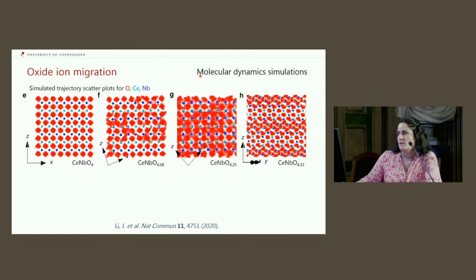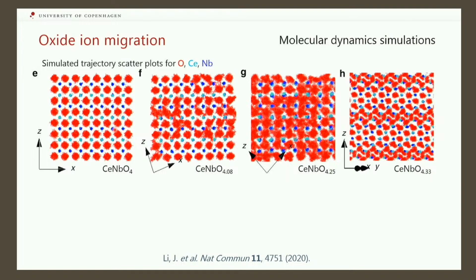So we have also seen earlier this morning molecular dynamic simulation. In this case, they are carried out to examine the diffusion of atoms in the lattice. So every time you see a connected red trajectory, for example, it is indicating that the oxygen can diffuse throughout the lattice. And you see, it depends on the amount of extra oxygen and depends on the structure.